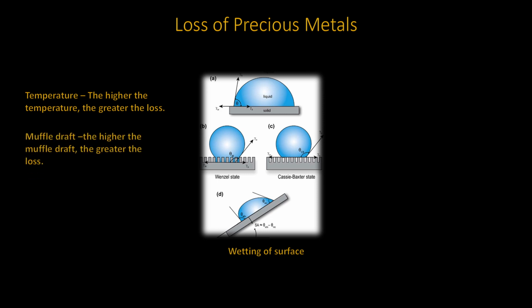The muffle draft is also a big one. It must be controlled one way or another. For a pot furnace, it takes a little experimentation. The air supply determines the oxidation rate. The ideal condition is 1 gram of lead converted to lead oxide per minute. Increasing the draft beyond the ideal condition generates more heat and raises the temperature, resulting in higher losses.